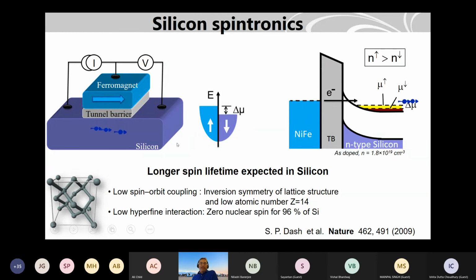What we found in the beginning was that it was very challenging to inject spin into silicon. In the previous case with gallium arsenide, they could epitaxially grow it and use the Schottky barrier between the ferromagnet and gallium arsenide to inject spin, because the Schottky barrier also acts as a tunnel barrier. But in silicon, if you put a ferromagnet on silicon, the interface will have some silicides that will dephase all the spins. So it's very important to get a tunnel barrier in between. That is the material point of view. It will also act as a spin polarized tunnel barrier, because tunnel barriers we know are good for spin polarized tunneling.